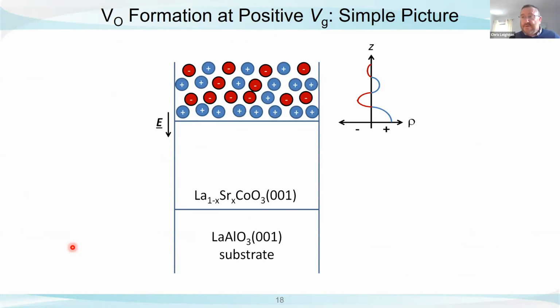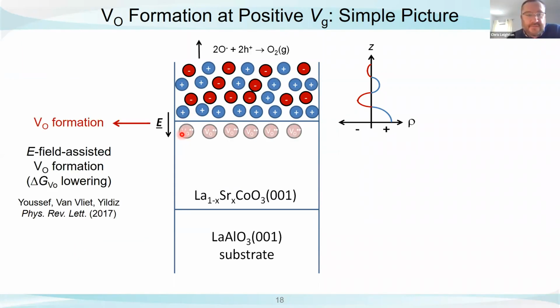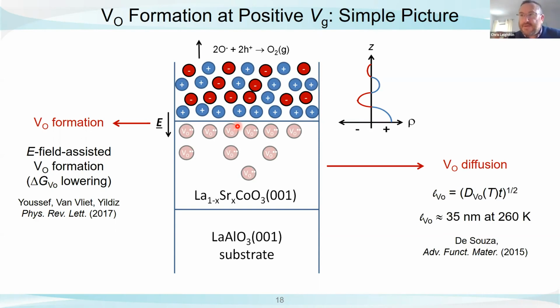So again, this is a very simple picture that we've developed. This is what we believe our electric double layer looks like at positive voltages. We have an electric field that looks like this. We believe that what happens at the very top surface is the electric field assists the formation of oxygen vacancies by lowering delta G_VO, which is already very small. That puts oxygen vacancies in the top 1 or 2 unit cells. And then we have a chemical potential gradient for oxygen. And the remarkable thing about the cobaltites, the really amazing thing about the cobalt-based perovskites, is oxygen vacancy diffusion is basically fast enough to do the rest.